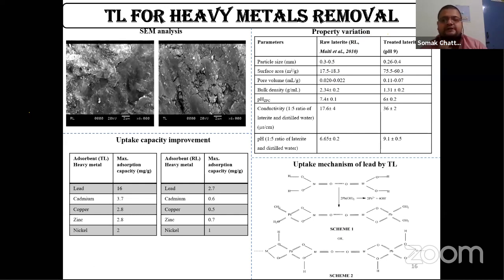Coming to the different characterization which we had done for heavy metal removal, we can see from the SEM analysis that the surface more or less looks plain, while after treatment there are different cracks and pores developed on the surface. From the property variation, the surface area initially for raw laterite, that is lateritic soil, was 17.5, whereas in treated laterite it increased comprehensively to around 75. The pore volume also increased, and the conductivity of the solution increased nearly double.